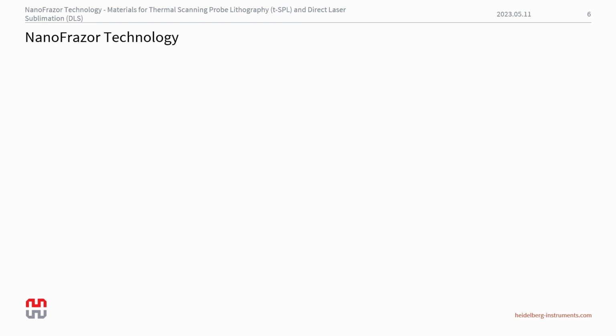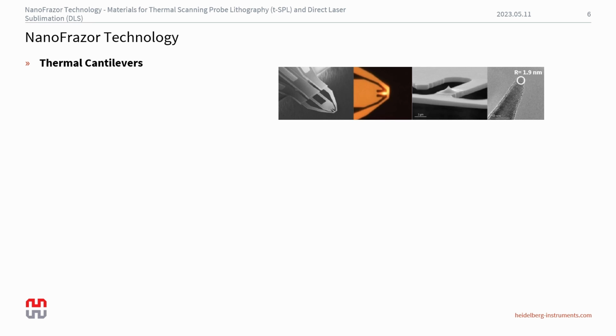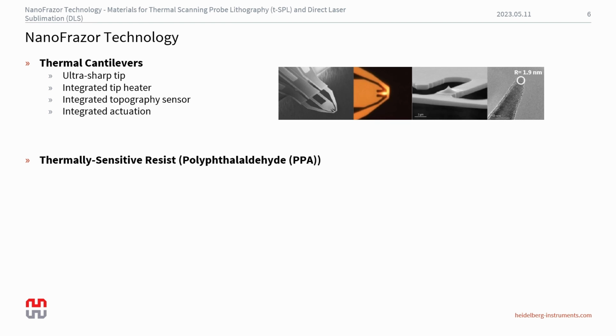So within the NanoFrazor technology, there are three key areas that allow us to do really nice lithography. And that starts with the thermal cantilevers. So these cantilevers have four characteristics that are quite important. They have an ultra sharp tip where the radius is less than 5 nanometers or so for interacting with the sample surface. It has an integrated tip heater, so you can locally and precisely control the temperature of the tip. We have an integrated topography sensor that's measuring the heat flow with respect to the surface. So that allows us to have sub-nanometer precision in the z-axis for grayscale lithography. And then finally, having electrostatic actuation on the cantilever allows us to also control the z position very nicely.